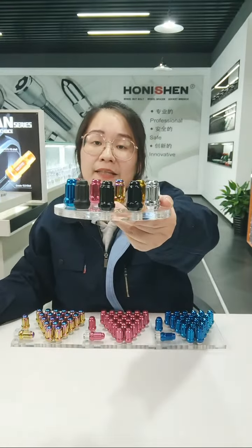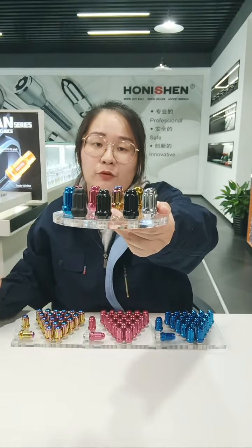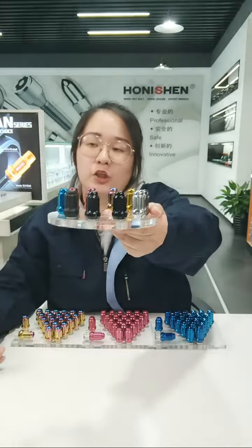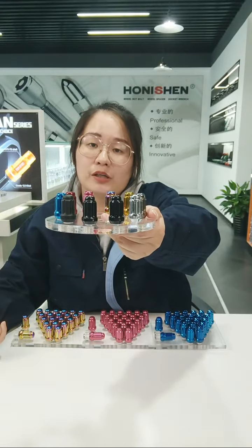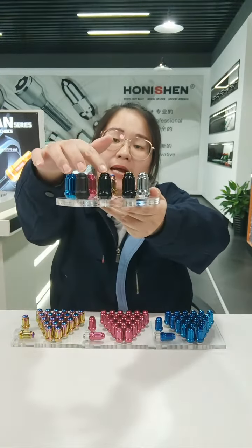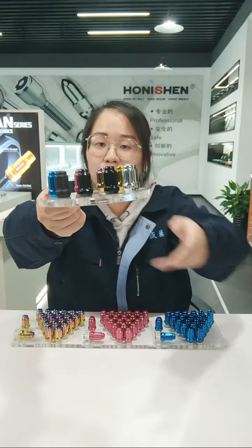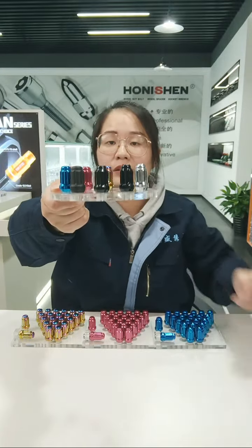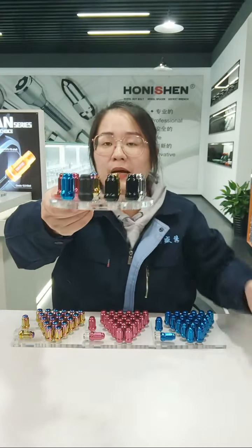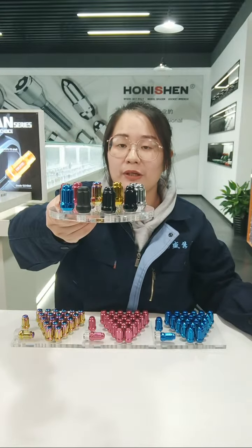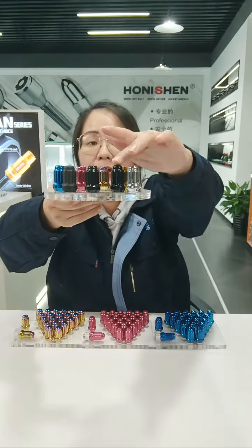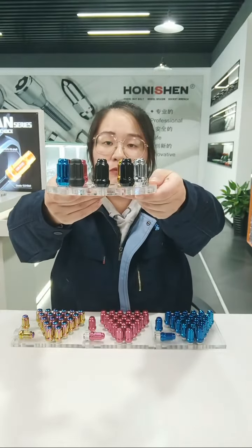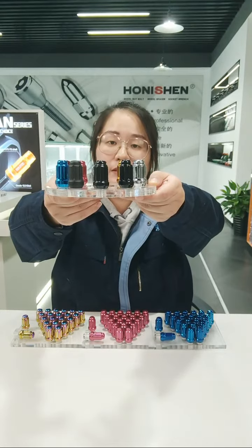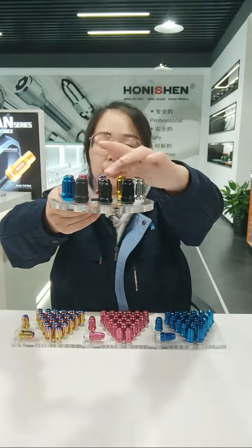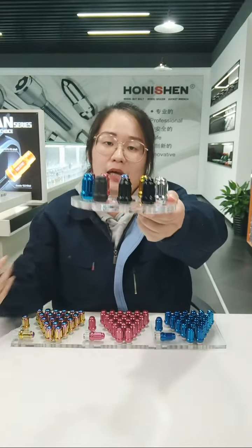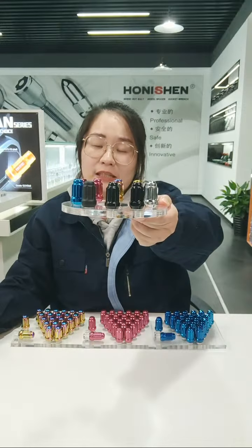First, the anti-rust performance is different. Black chrome could pass over 96 to 200 hours salt spray test. Black electrophoretic could pass over 48 hours salt spray test. And this matte black could pass over 200 hours salt spray test. So black chrome and matte black have better anti-rust performance. For black electrophoretic, the anti-rust performance is not very good.